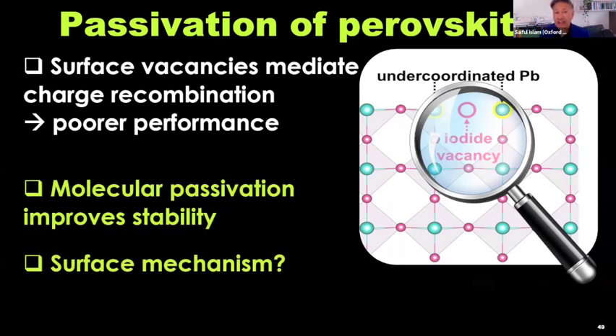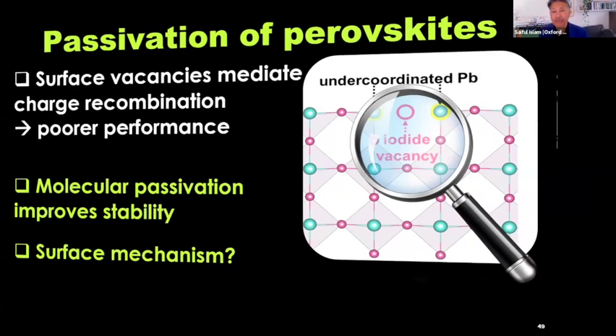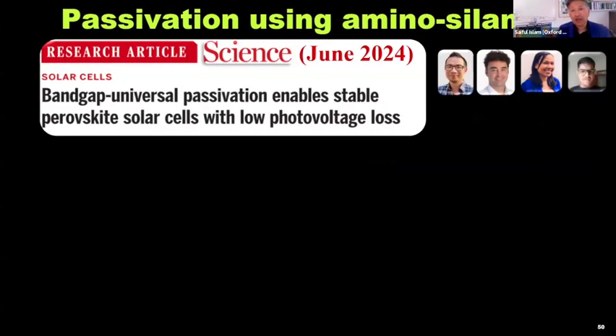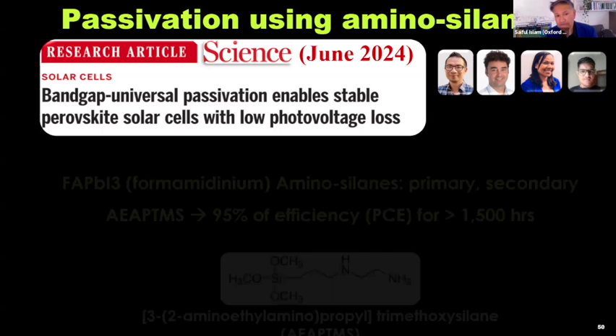So molecular passivation can improve their stability. But what is the surface mechanism? What is the atomistic mechanism going on? This is recent work with Henry Snaith's group and Nikita Noel here at Oxford, in Oxford Physics, and work with my group led by Vikram. And we published this last year in Science. We found a band gap universal passivation that leads to stable perovskite cells with low photovoltage loss.